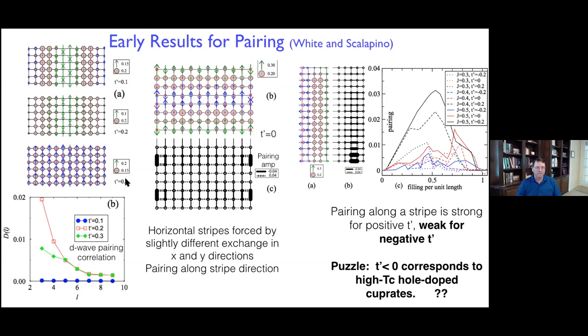If we crank up the T prime, we see a uniform state. It still has a substantial amount of magnetism. It's broken symmetry, but it's still there. And then we measure pairing correlations. We make a D wave operator at one point and measure it at another point. At T prime equals 0.1, we're sitting here with essentially no response. But with the bigger T prime, we're seeing pairing correlations that are fairly significant.